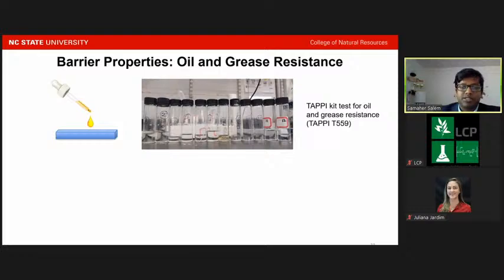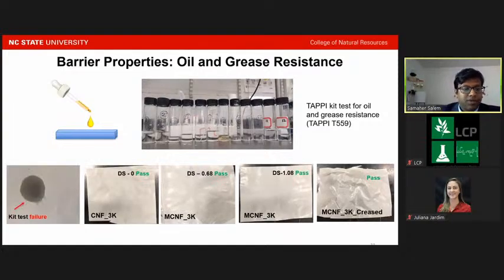Then we also did the barrier property tests, measuring the oil and grease resistance. We used the TAPPI standard test, and we could find that the cellulose, modified cellulose, unmodified cellulose, and even the creased surface of the modified cellulose show very high oil and grease resistance. All of them pass the 12 kit rating, compared to the regular paper, which shows failure on the left side of the picture.